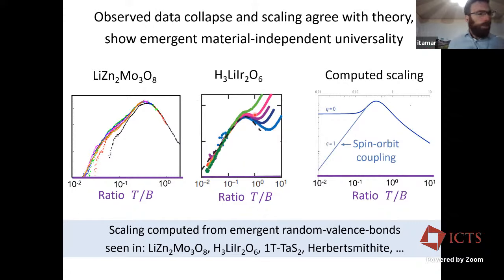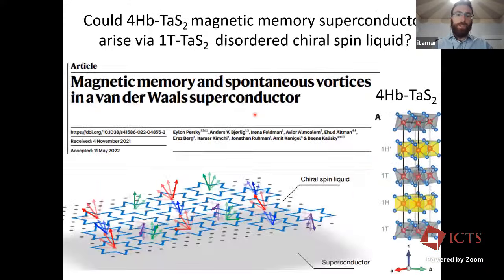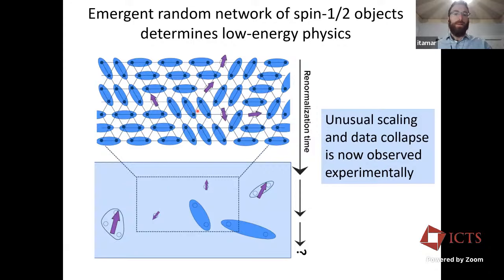Right. So I'm trying to remember. I guess copper iridate also has some of the magnetic sites with substitution. Yes. So then it's this disorder, but in addition to bond randomness, you also have magnetic site dilution. So let me say two things. First, in some ways, you can say that's just a shortcut to what we get here. The theory I had was, even with just bond randomness, I end up with these vortices that carry spin. But if you're just adding or removing magnetic sites, then already you can get these spins. So that's what I think happens in Herbertsmithites in exactly that way.